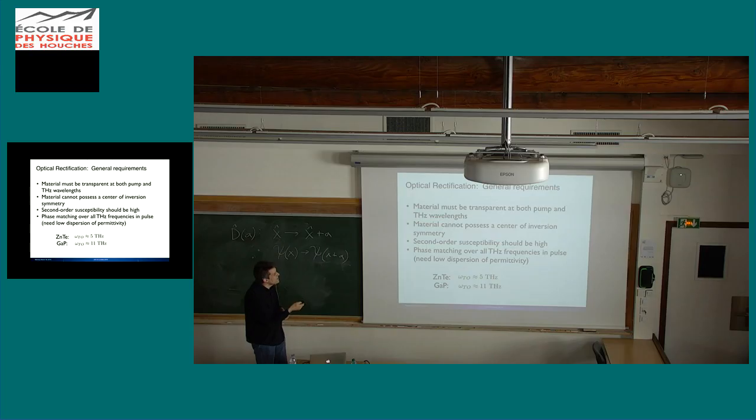All right, so you have to have a transparent material. You cannot possess inversion symmetry. That sort of goes together. The second order susceptibility should be fairly high, and you want phase matching over all the terahertz frequencies in the pulse. So that usually is a limiting factor. That's actually what oftentimes causes the limited bandwidth that gets emitted from an optical rectification process. I was trying to think last night if I could really prove this. I think it may be possible, but all the materials I know that don't have a center of inversion symmetry have an optical phonon mode that is IR active